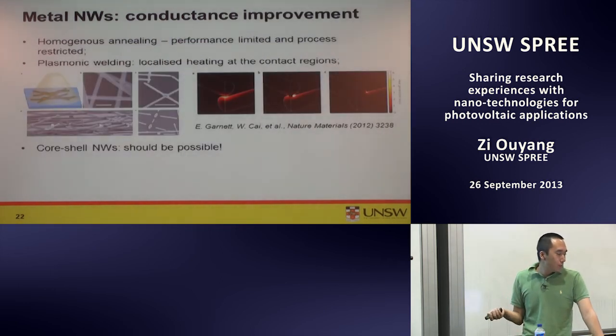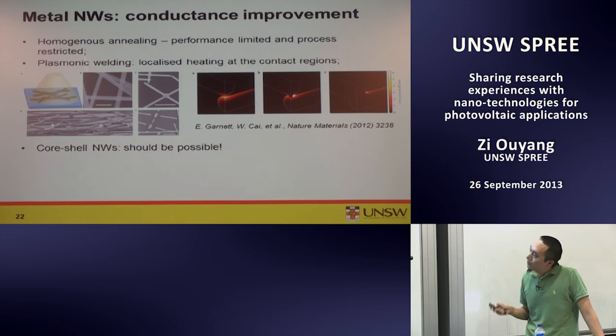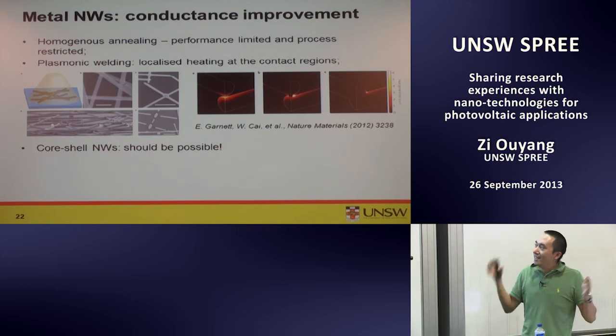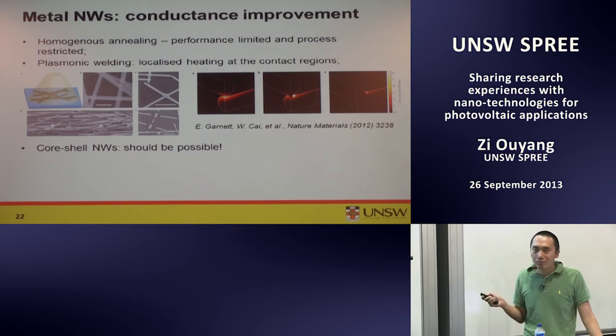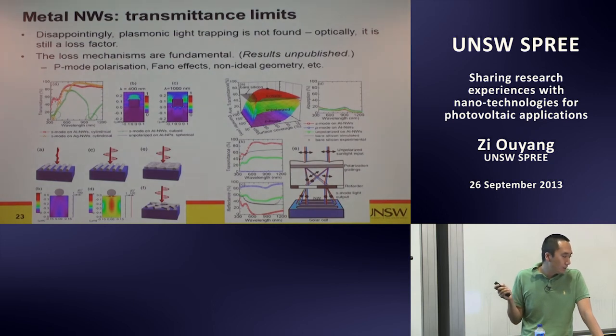So conductance improvement. This is we did homogeneous annealing. Its performance limited and process restricted because you need relatively high temperature. But a bunch of smart guys in Stanford, they sort of use the light plasmonic effect, so if you have the light shining on the network, actually the heat will only generate at the position where you have the largest resonance. So you have local heat here at the junctions, and at the interface between the substrate and the nanowires. So actually you heat melt it down nicely, but keep the rest cool. So this is really a cool technology. I think if nanowire is gonna work one day, this is a must-have technology for that. So transmittance limit, this is some unpublished results.